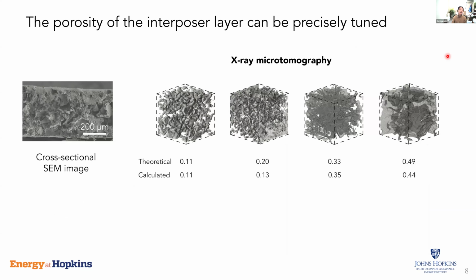And the important thing is that by tuning the resin and sodium chloride porogen ratio, we can really tune the porosity very precisely in this kind of wafer. So this is a cross-sectional image of the resulting wafer material. And as you can see, as I change the porogen content, which is a theoretical pore volume introduced by the porogen, and compare with this X-ray tomography determined porosity, they show a pretty good agreement, so indicating a good tunability of this material.